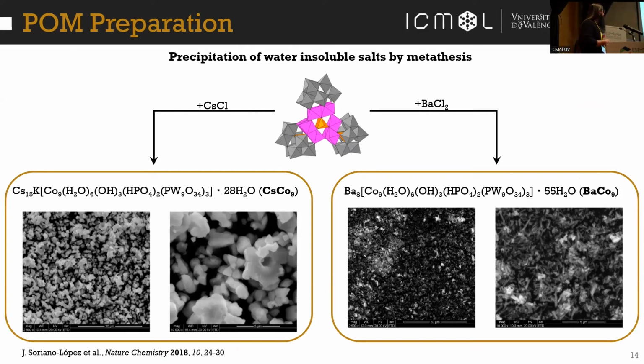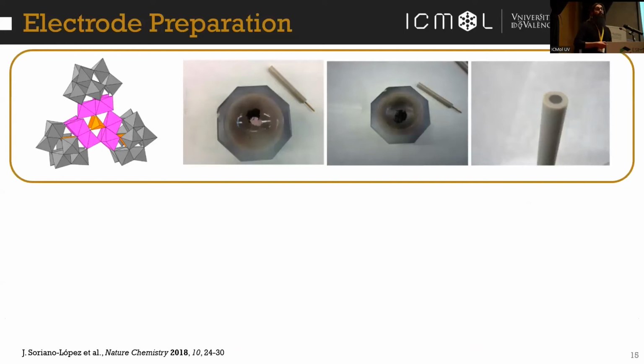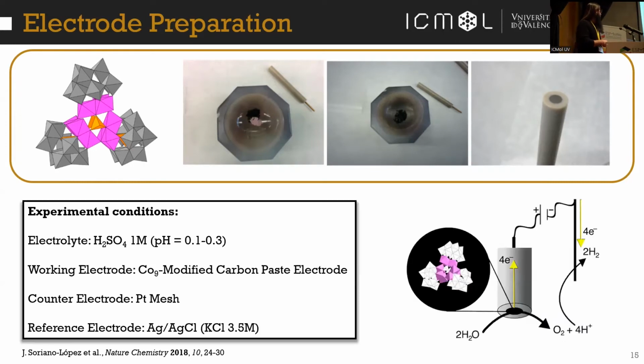We took these salts and we prepared modified carbon paste electrodes. Carbon paste is basically amorphous carbon with some inorganic binder, and it serves as a support for these solid-state polyoxometalates, and also to increase the conductivity because polyoxometalates are quite insulating. For doing this, we mix the polyoxometalate and the carbon paste in a mortar, so that we have a homogeneous blend, and we introduce this blend inside the pocket of the electrode. So we have our electrode ready, and in this case, we use 1 molar sulfuric acid as electrolyte, which gives us a pH around 0.1 to 0.3.